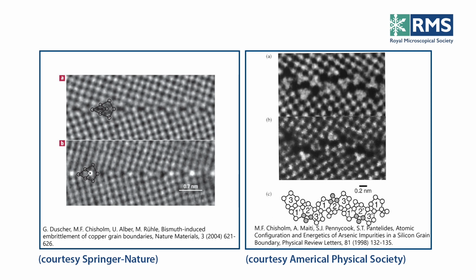And the next slide shows you a great effect of this STEM imaging, and that is the incoherent scattering you get is sensitive to the strength of the scattering of the atom column, and that means it's sensitive to the elements producing the contrast. And this shows a beautiful picture of the embrittlement of copper grain boundaries by bismuth, which in principle is of great importance in the embrittlement of grain boundaries in metallurgical applications. And there's another picture here of arsenic impurities in silicon grain boundaries.